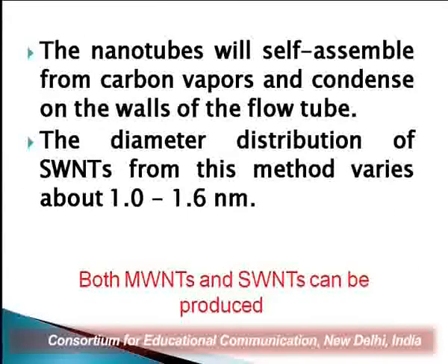The nanotubes will self-assemble from the carbon vapors and condense on the walls of the flow tube, and the diameter of the single wall carbon nanotubes prepared from this method is 1 to 1.6 nanometer.